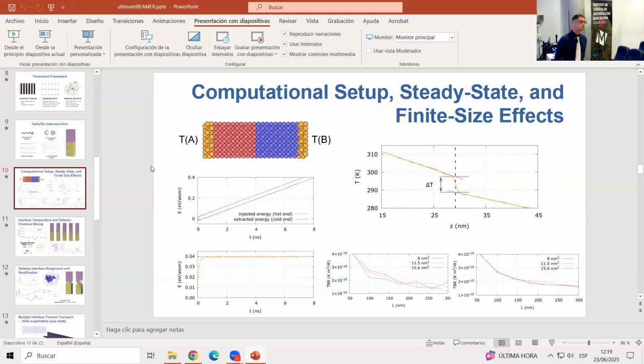One general question I would ask you: you chose a very interesting interface, which is germanium gallium arsenide. As you explained very well, the lattice mismatch is basically zero, 0.5% or something like that. There are also two other very interesting things there: the acoustic mismatch is very small between the two materials, and the thermal conductivities are very similar. So usually you have very good phonon transport at the interface. You picked a nice interface, let me put it that way, in terms of having a high thermal conductor.